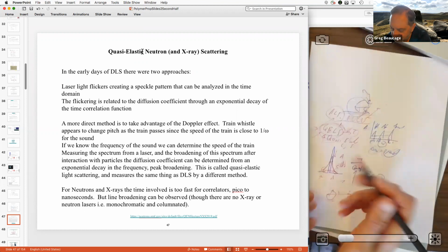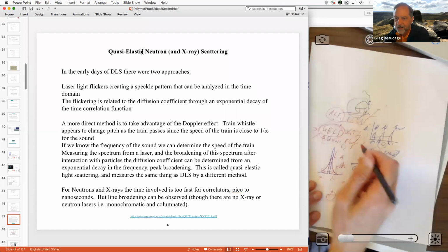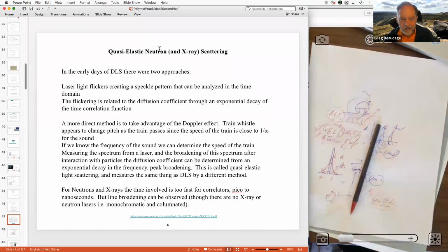That's a related technique, but basically quasi-elastic neutron scattering is directly related to dynamic light scattering. It's analyzed the same way. You get a relaxation time. From that, you look at Brownian motion, you get the diffusion coefficient, you get something like a hydrodynamic radius. So it's directly linked to DLS, kind of DLS for neutrons. It's DLS where the beam is an angstrom or 10 angstrom, one nanometer beams. And for X-rays, it's 1 angstrom beams, right?